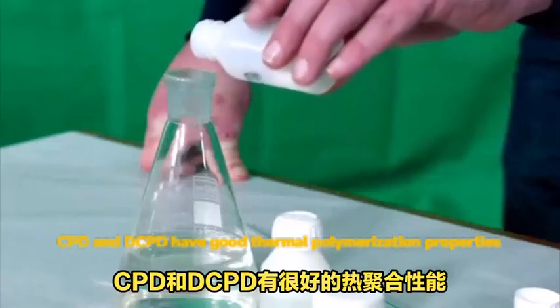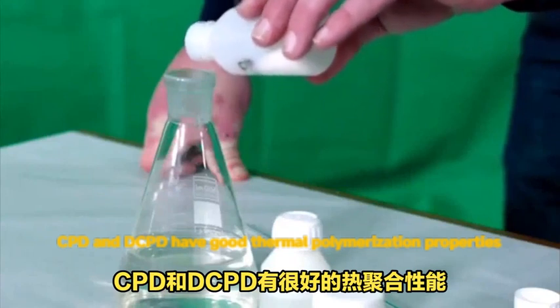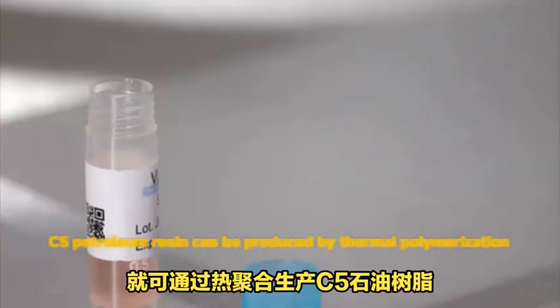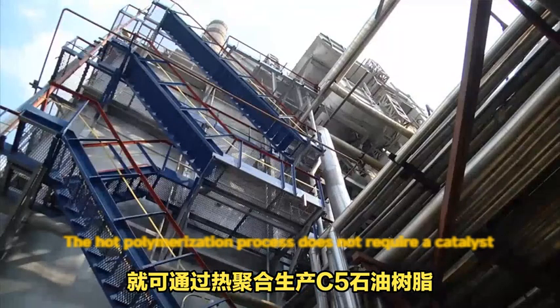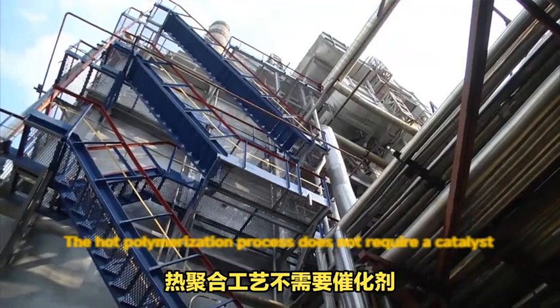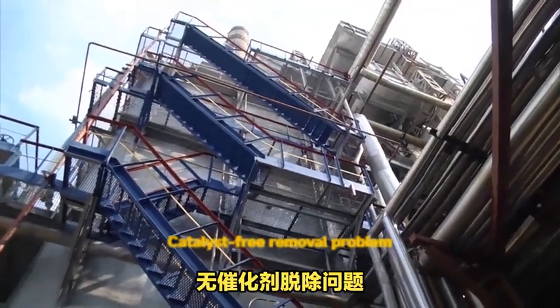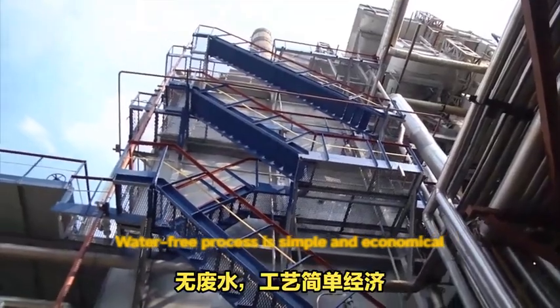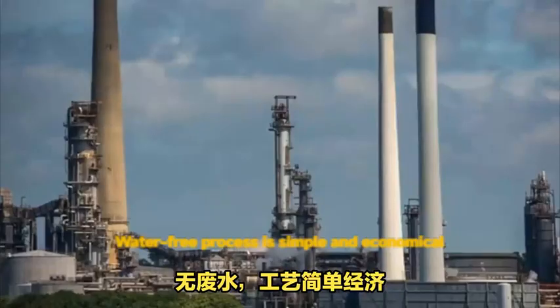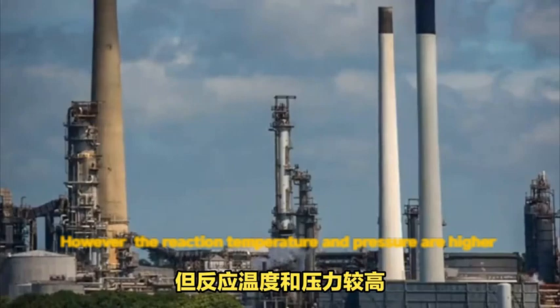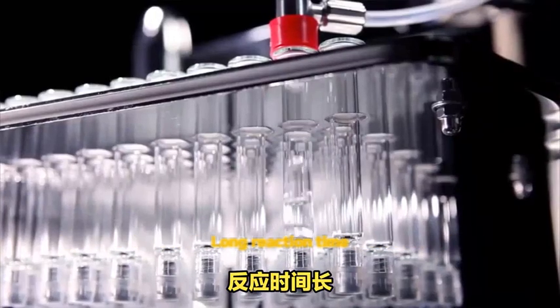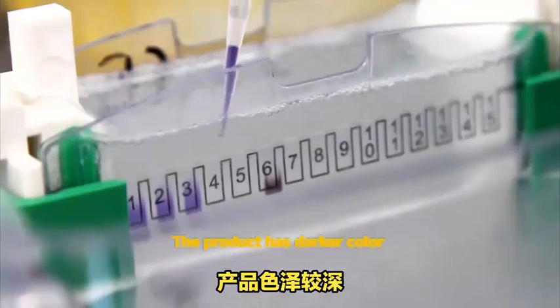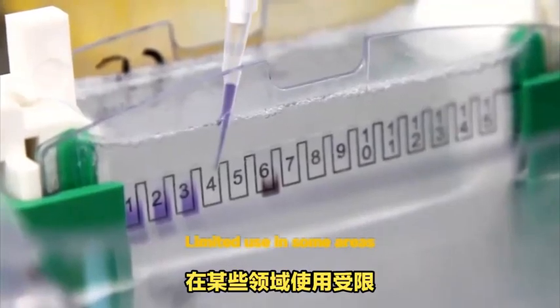CPD and DCPD have good thermal polymerization properties. When the CPD and DCPD in the C5 or C9 fraction are above 35.0%, C5 petroleum resin can be produced by thermal polymerization. The thermal polymerization process does not require a catalyst, so there is no catalyst removal problem. Water-free processing is simple and economical. However, the reaction temperature and pressure are higher, the reaction time is long, and the product has a darker color, so its use is limited in some areas.